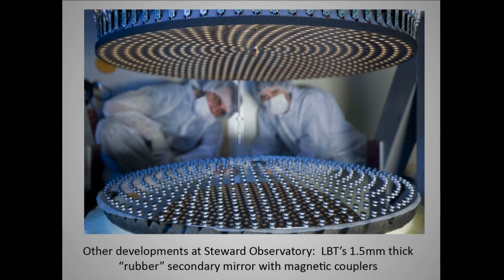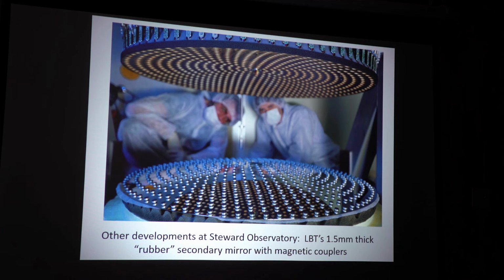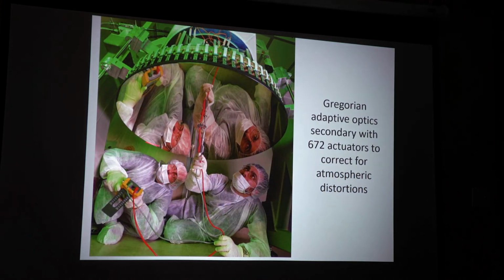These are just a couple things in passing. This is old technology. This is probably 8 or 10 years old now. But one of the things that we did at Steward, we built a secondary mirror for the Large Binocular Telescope that is 1.5 millimeters thick. It's precisely aspheric, 1.5 millimeters thick. It's got 670 magnets glued to the back of it, and they interface with little voice coils up here, and they can put forces on that mirror to do atmospheric corrections using the Gregorian secondary mirror.